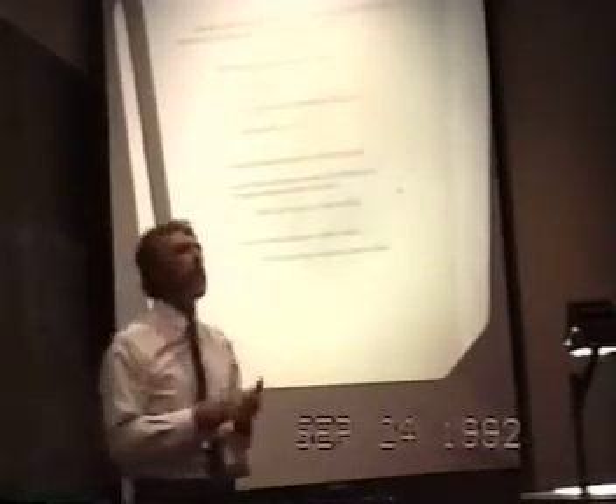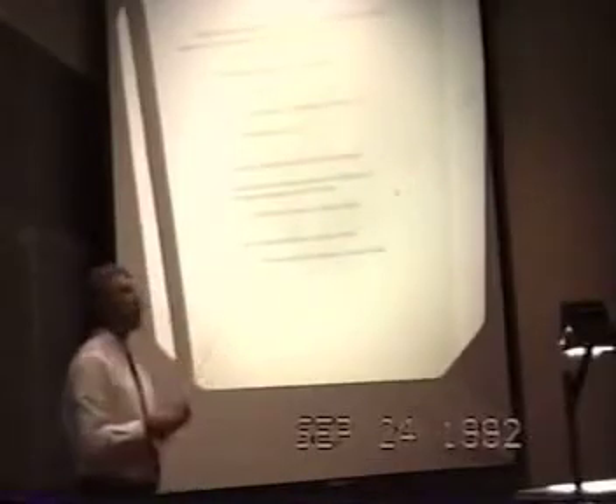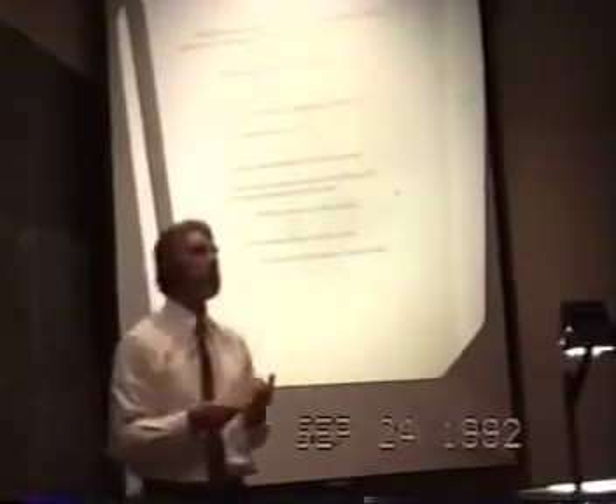Not only must we achieve this loading, and this loading is relatively easily achieved and relatively quickly achieved, it must be maintained for a critical period. That period is about 300 hours for a 3mm diameter rod. It's less for foils. But the important feature here is that that critical period is longer than the diffusional time constant of hydrogen and its isotopes in palladium.